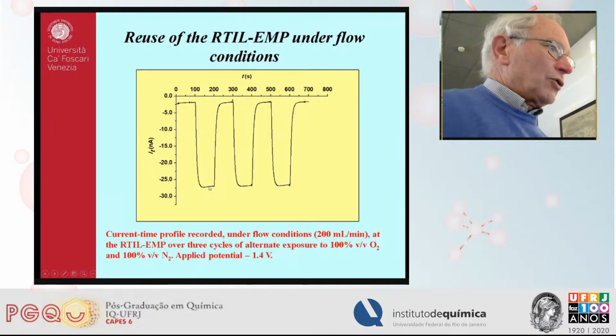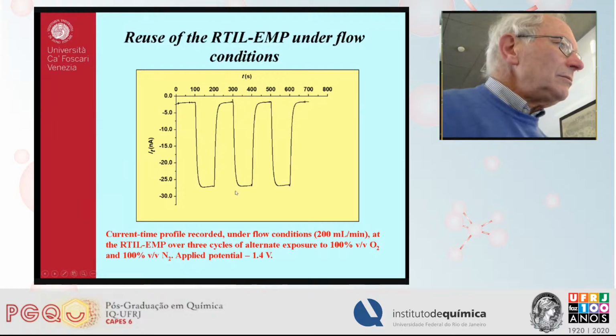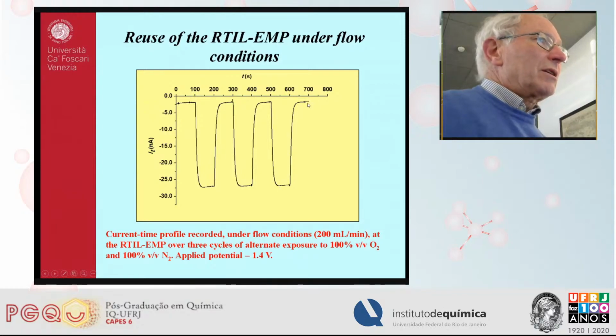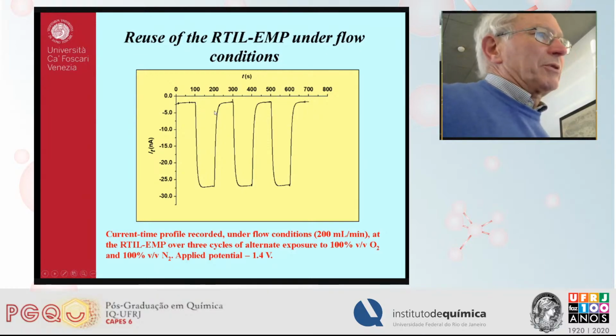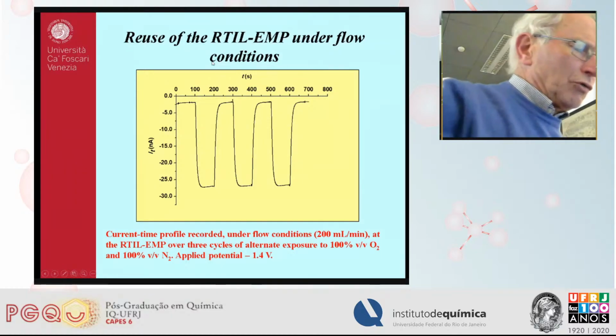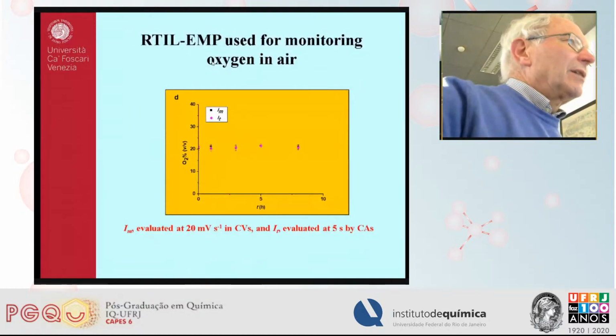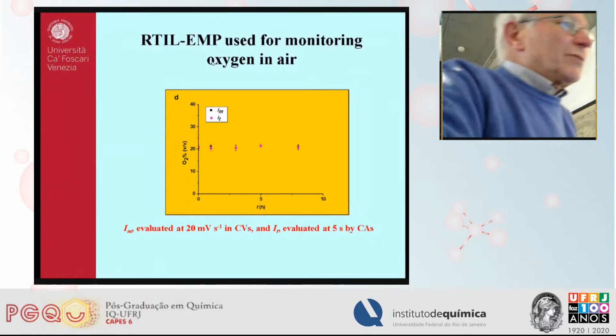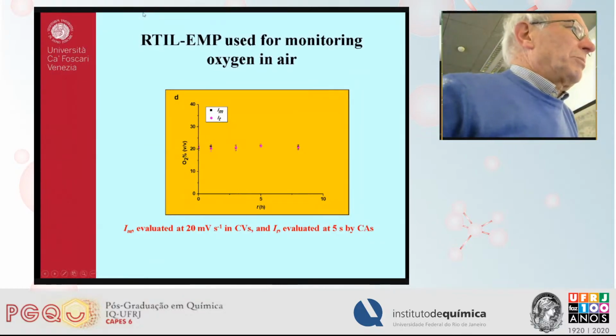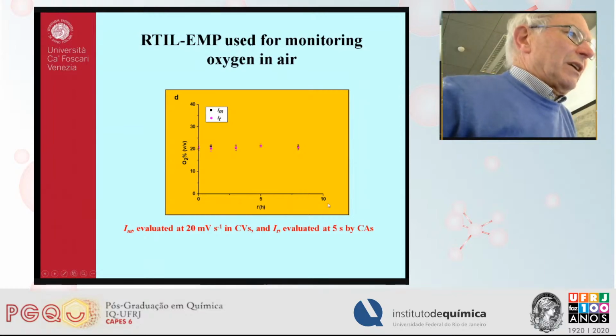keeping the oxygen atmosphere for a given time, then sending nitrogen into the container, so the current decreases, and so on for several times. As you can see, the reproducibility is very good. So you can use this system many times, which means you can monitor the oxygen concentration in a simple way. And to verify that this was the case, we used this room temperature ionic liquid microprobe for monitoring oxygen in air for several hours.